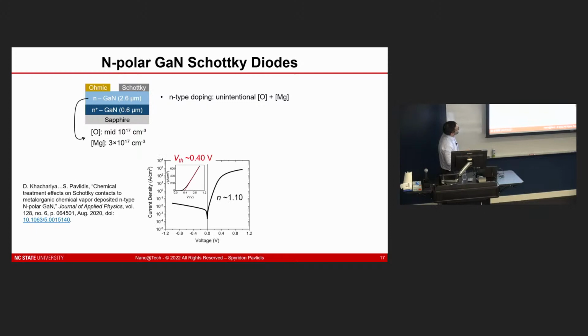When we made these devices, we characterized these as a control on unprocessed, pristine surfaces, if you will. And we set a baseline for very high quality Schottky diodes with low ideality factors. And now you can see a turn on or threshold voltage of 0.4 volts. Gallium polar GaN typically has a larger turn on voltage when you make Schottky diodes, in the range of 0.6 to 0.7 volts or so. So this is already a little lower, and you can see that that will trickle down later when we make these devices for high voltage applications.